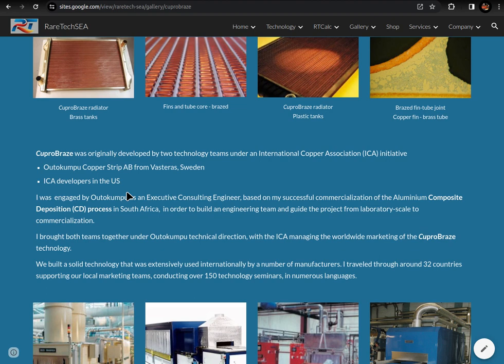And when I got on board, frankly, they didn't even have a tube to header joint. They had pretty good tube to fin. That was nice. This was good. But when you start to get into these areas here, it's very, very tricky. And you've only got one shot, when you pass this thing through a brazing furnace. It's got to be perfect. And there was a problem with the tube to header joints and these side rail joints. These are not too bad, but the tube to header was a real issue. And then doing the tanks was an issue as well.